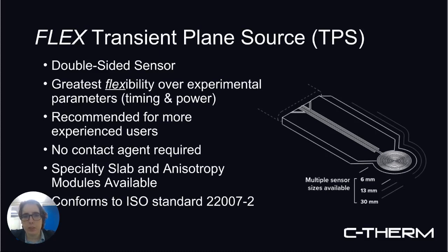So the transient plane source method, the probe looks as you can see on the right-hand side of the image. It's a very thin layer of nickel, which is etched into a double spiral pattern called a bifilar spiral. And then that is basically insulated on either side with a thin layer of polyimide, which is just there to act as a dielectric material and electrically isolate the probe material, which is made of nickel.